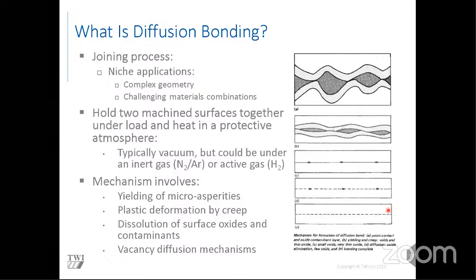Because we're heating these parts up, we typically do this in a protective atmosphere. So that could be a lack of atmosphere, a vacuum, or we could use an inert gas such as nitrogen or argon. There's also some research being carried out looking at active gases, so a partial pressure of hydrogen could also yield some advantages.